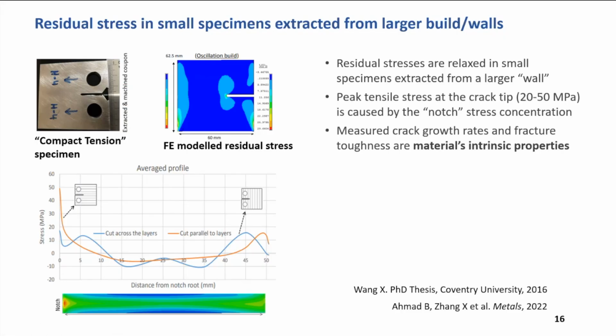It's not a real residual stress, because we also verified this by not having a notch and just a tiny small block extracted from the walls. And we found in this 2022 paper that residual stresses are relaxed. So what I want to say, the third bullet point, is that the mechanical properties I present today are